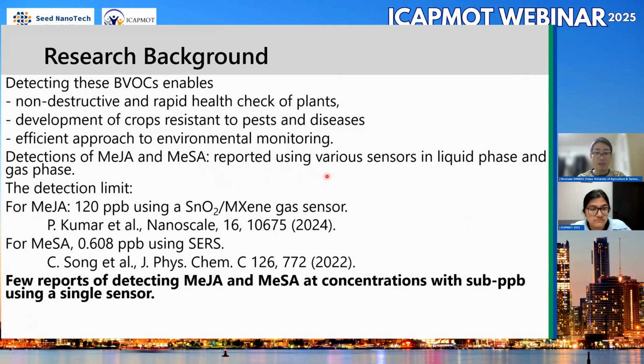was reported using various sensors in liquid phase and gas phase. The reported detection limit for methyl jasmonate is 120 ppb using tin oxide MXene gas sensor. And for methyl salicylate, 0.608 ppb was reported using surface-enhanced Raman scattering. However, there are few reports of detecting methyl jasmonate and methyl salicylate at sub-ppb concentrations using single sensors.